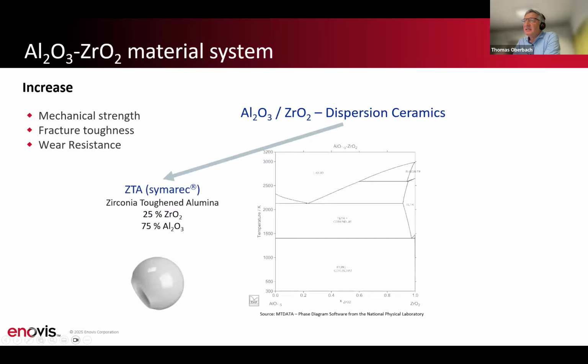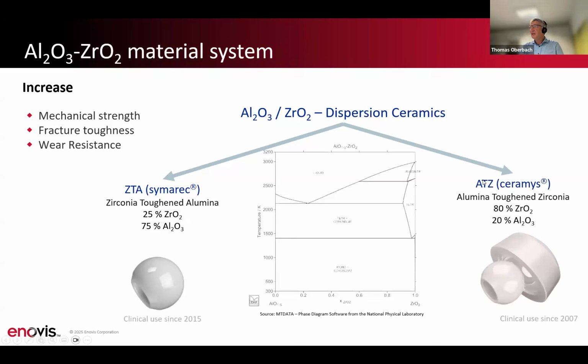And we also developed a ZTA ceramic. You see here the chemical composition. It contains 75% alumina and 25% ZrO2, stabilized with yttria. On the other side, we also developed an ATZ ceramic, which is zirconia-based, also stabilized with yttria, and combined with 20% alumina. The trade names are Symarec for ZTA, and for ATZ, it's Ceramys.